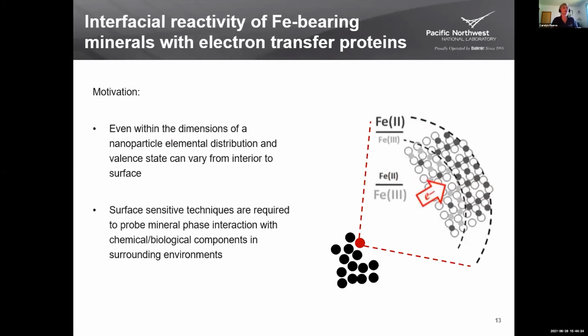So that understanding of the magnetite structure was just for mineral phases, and showed the application of these soft X-ray techniques for looking at interfacial reactivity. And so we wanted to be able to combine that with laboratory-based techniques that tell us about the bulk iron 2-3 ratio. And it turns out that XRD is very sensitive because of the different relative sizes of the iron 2 and the iron 3 cation to tell you about what's happening with the bulk. And so combining those techniques, we can look at how electrons flow from the interior of the particle to the surface, and then ultimately engage in interfacial reactivity. And these are some examples of looking at that with now biological components that might be present in the environment.